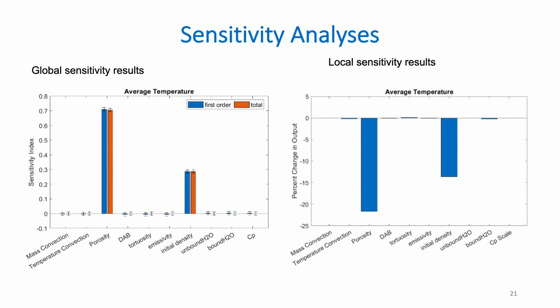We also conducted sensitivity analysis of key modeling parameters, both using local sensitivity analysis, which considers how much variation happens for a 1% change in that local variable, and also global sensitivity analysis, which considers the net effect of that parameter in the total variance. And both studies show porosity and initial density as the most sensitive parameters.